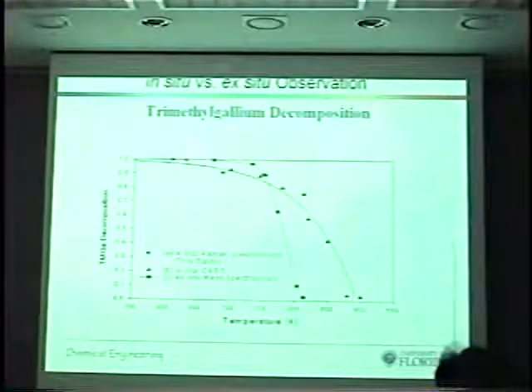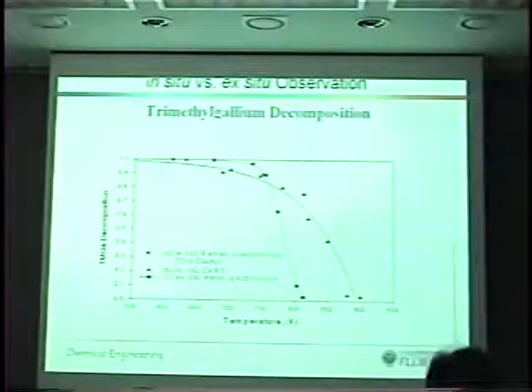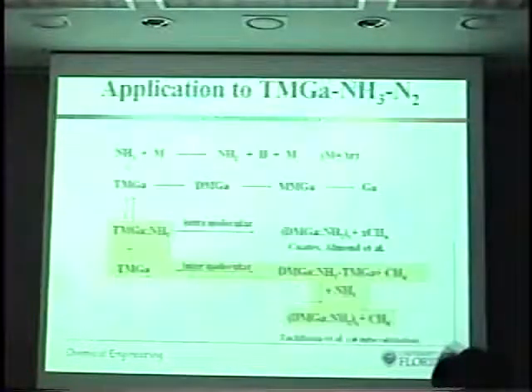We also then looked at trimethyl gallium decomposition, and consistent with other in situ measurements in the literature, we get a much lower start temperature extending over a larger temperature range, which would give you a different rate than that measured by ex situ techniques such as mass spectrometry. But we were able again to identify the rate constant for breaking that first carbon-gallium bond.